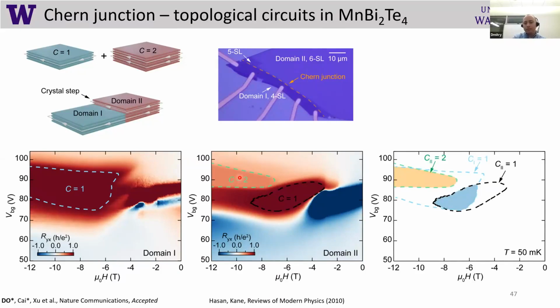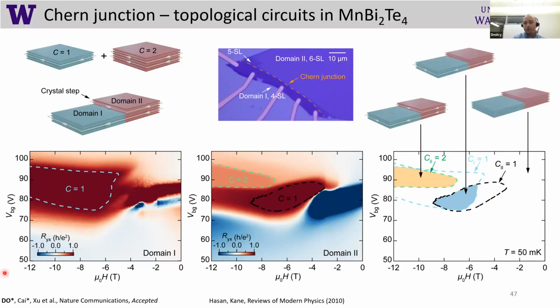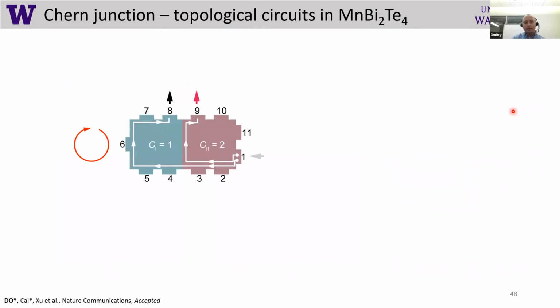If we overlap them, we can see that the situation I described in the beginning is possible in this device, meaning that the blue line and the black line overlap in 2 regions. In this yellow region, we can form this Chern junction. In this blue region, we can turn off the edge state because now Chern number is 1 everywhere. And also by changing magnetic field to lower values, we can essentially switch off these edge states. So now we can see and test how this works.